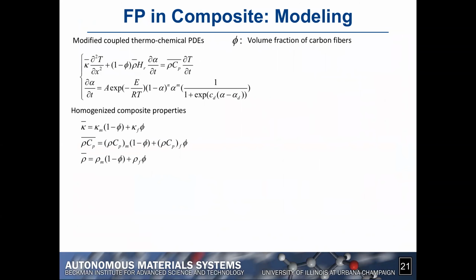So, from the modeling point of view, the simplest model we came up with for modeling frontal polymerization in composites is based on exactly the same type of coupled partial differential equations as the ones I showed before for pure DCPD, except that now we use the average thermal properties and densities, or the homogenized ones, for the unidirectional composite system, right? So the quantities with the overbar correspond to the homogenized properties. And for this simple problem, the simplest way to approach this is simply to use the rule of mixtures for that particular quantity. Now, the fiber volume fraction, which is denoted by phi, also enters in the term associated with the exothermic heat of reaction.